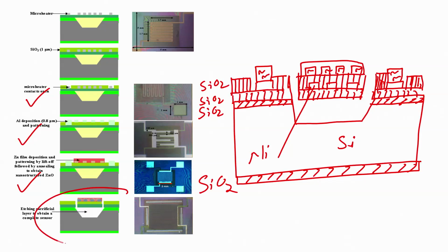So, we have the sensor and you can see the role of zinc oxide in the pit was to act as a sacrificial layer. This particular way of removing zinc oxide is your surface micro machining. So, we are combining bulk micro machining with surface micro machining to have a sensor on just 1 micron silicon dioxide. This silicon dioxide that we have grown initially using wet oxidation is 1 micron. So, about 1 micron thick diaphragm or 1 micron thick bridge, we have created an entire sensor.